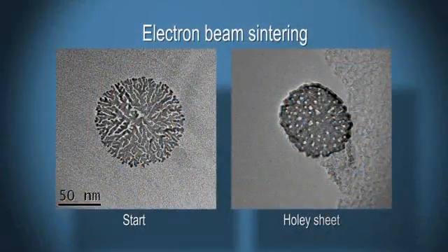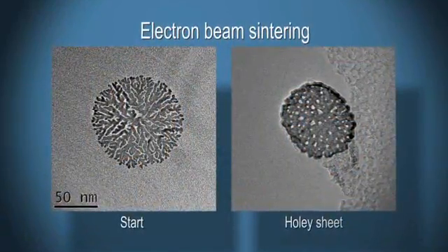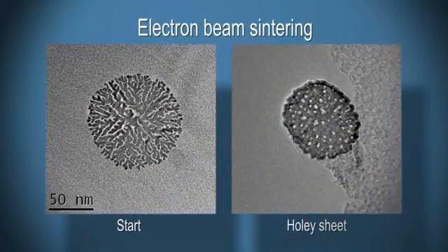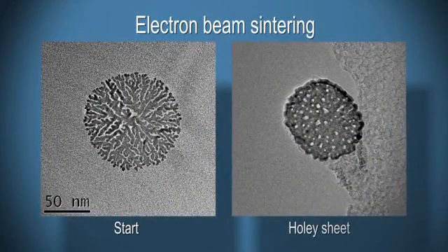So the spacing between the arms of the dendrites start to close up in places and leave holes in the sheet. And that feature then preserves the surface area which you need to carry out catalysis and makes the electrocatalyst used in the fuel cell more durable and perhaps can give you advantages in longer-lasting fuel cell function.